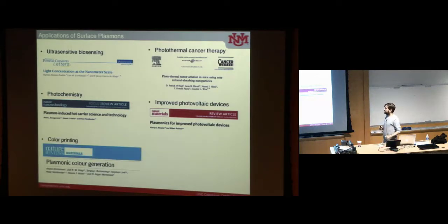More recently, the community is also looking at using plasmons to produce colors. Definitely, you've seen an example, like the Lycurgus cup, which is a very beautiful example of how, by engineering the shape and the size of plasmonic nanoparticles, you can produce very vivid colors, which are structural colors. They don't come from a chemical origin. They are just due to the geometry, and therefore they are expected to be much more robust than pigments or dyes that typically tend to photobleach as time goes.